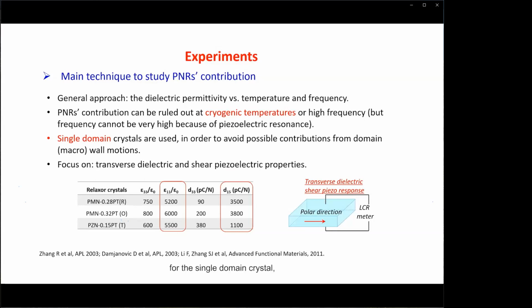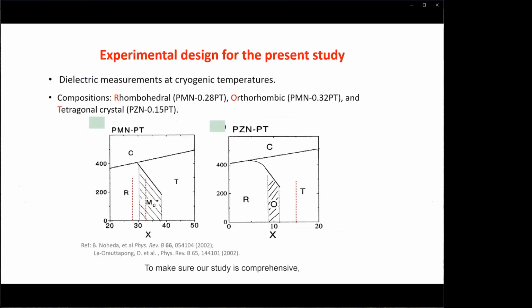For the single domain crystal, transverse dielectric and shear piezoelectric coefficients are much higher than their longitudinal counterparts, so we focused on the transverse properties. This schematic shows the sample for measuring the transverse dielectric permittivity and the shear piezoelectric coefficient. To make sure our study is comprehensive, we selected three typical ferroelectric phases: rhombohedral, orthorhombic, and tetragonal phase. As shown in the phase diagram, there isn't any phase transition below room temperature for all three crystals.